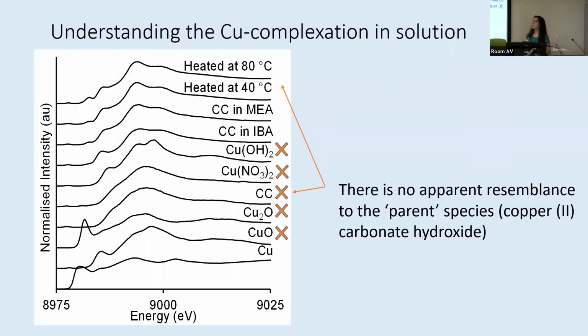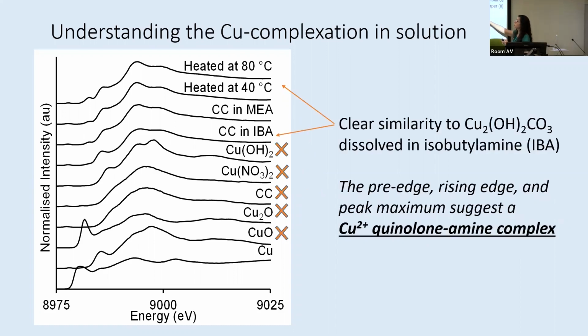And so the baseline that I just showed you is part of the reason we use that to try to understand what the copper is doing. And so we needed to understand what the copper is doing. And what's really interesting is that the addition of a copper carbonate into this type of solution shows no consistency with either the parent complex or with any of these other complexes which we would anticipate. So why does this matter? Because we've demonstrated that in the presence of copper carbonate, you appear to get no corrosion, but the mechanism and the chemistry behind it are entirely unknown. And so with this data, we've been able to establish that as we start to look at our copper carbonate in things like isobutylamine, we can start to see similarities.